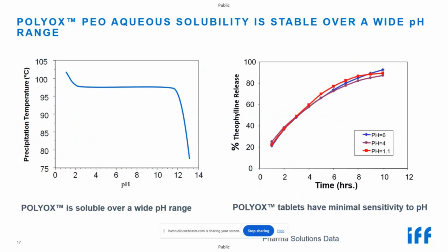Polyox, polyethylene oxide, makes a good choice for matrix tablets because its solubility is stable over a wide range of pH that include those found in the gastrointestinal tract. The graph on the left shows the precipitation temperature of PEO in water at different pHs from 1 to 13. The precipitation temperature is relatively stable around 95 to 100 degrees Celsius when the pH is less than about 11. You can see it's very stable. When it reaches around 12 or 13, you see this drop off in the precipitation temperature, indicating that the polymer is crashing out of solution.